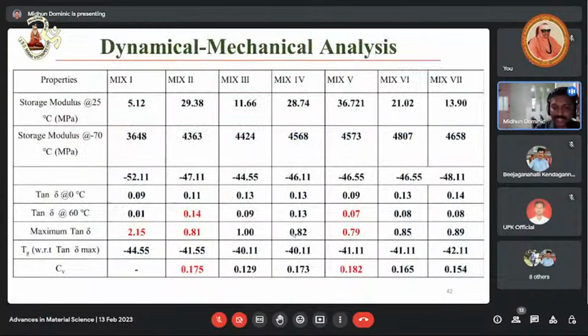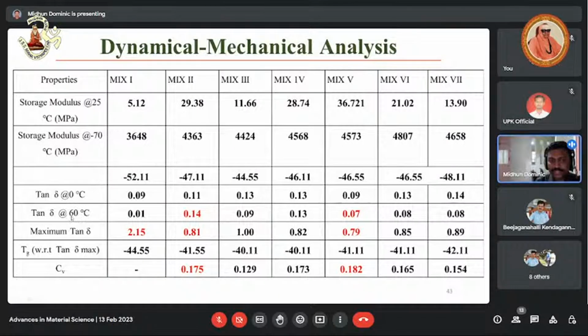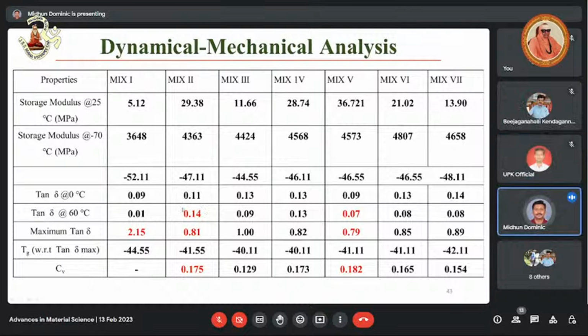And look at these tan delta values from the DMA analysis. Tan delta at 60 degrees Celsius is a parameter that determines rolling resistance. If we use carbon black 50, it is 0.14. But if we use carbon black 50 along with 1.5 phr of chitin nanofibers, the tan delta at 60 degrees Celsius decreased from 0.14 to 0.07. So about 50% decrease.